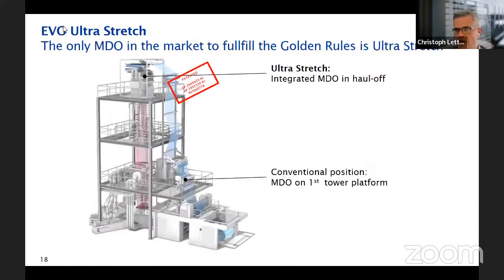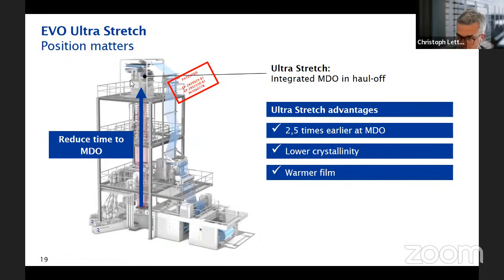Well, in that sense, Reifenhäuser came up with a solution where a full scale MDO with up to 12 rollers is integrated into your haul-off, instead of having it somewhere in a conventional position on the first floor tower platform, or sometimes we see this on the second level as well. But the earliest possible position is for sure within the haul-off. So here we have a full scale MDO, which means if I compare the position from this one to that one, that I meet the MDO 2.5 times earlier. So the film is warmer. I said this is important. It should be as warm as possible when it hits the MDO. The degree of crystallization will be lower. This will positively play on the stability of the stretching process.